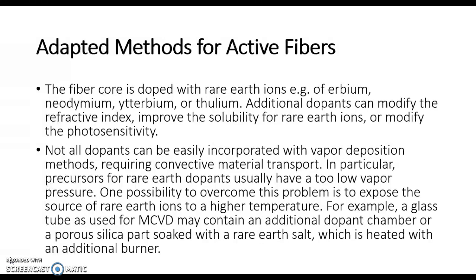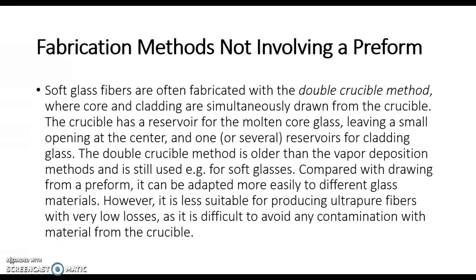Later on, the preform needs to be further processed to form a dry and compact rare earth oxide layer. An alternative technique is direct nanoparticle deposition from some aerosol. This method allows for high doping concentrations with good homogeneity and accurate control of the doping profile.